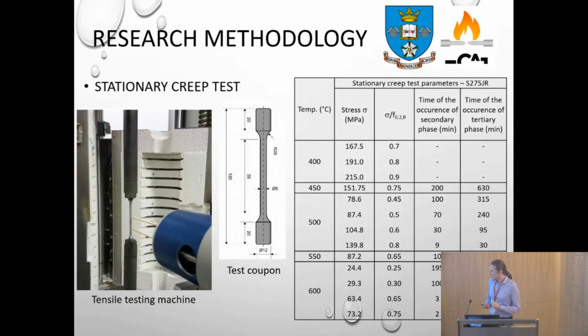For the stationary creep tests that we've done, we selected the range of temperatures. We've decided to go with the minimal temperature of 400 degrees. So 400 degrees in steel is basically the temperature at which yield strength is being affected. We suspected that the onset of creep will be correlated with the start of the reduction of the yield strength. And the temperature of around 600 degrees is basically a 50% reduction of the yield strength, and that's supposed to have an effect on creep as well, in terms of the increase in creep strain.